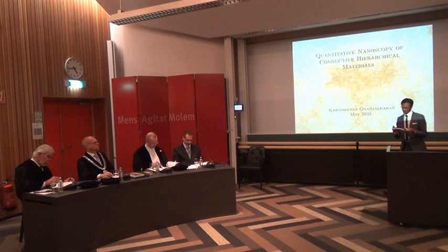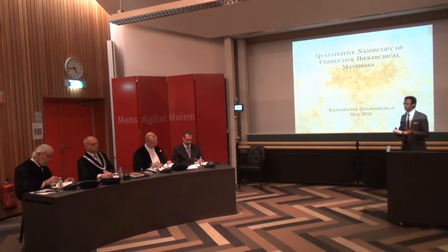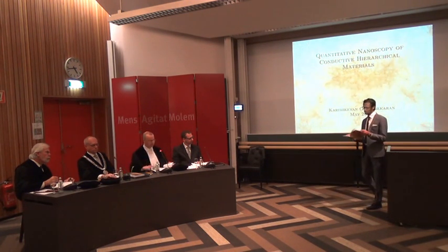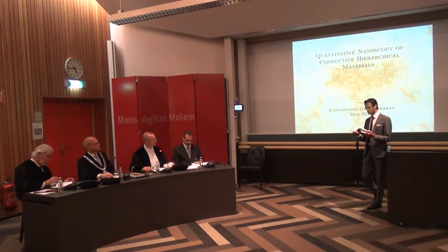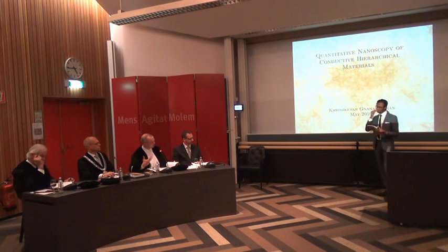So in case of 1 micron thick section, I don't think the section thickness itself is 1 micron. It would be something like 800 nanometer or 900 nanometer. But in case of 100 nanometer thick section, it would be 150 nanometer or something. So this is the same effect that you are seeing on page number 59 also: because of the fluctuation in the section thickness, there is a little bit of shift here and there. But for me, it seems a bit slightly systematic, so I was wondering whether there is some explanation for this.